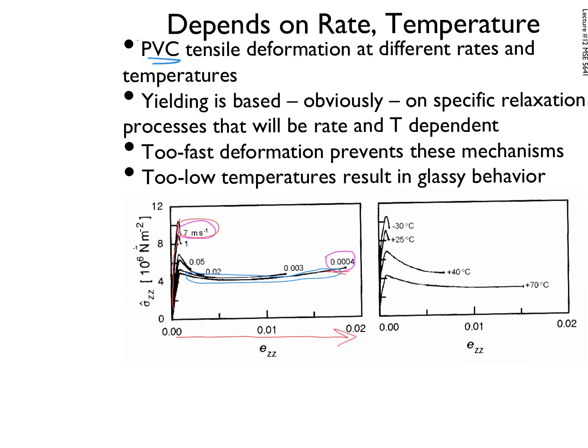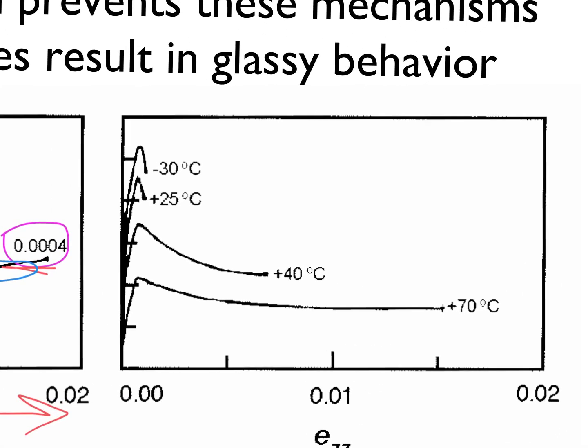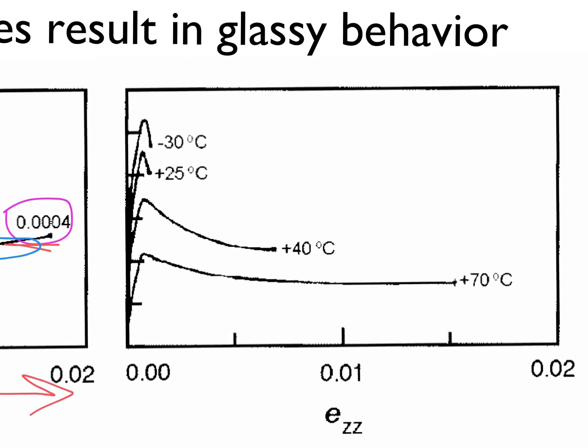And then in the context of temperature, we have a very similar behavior, and this is the one where the stuff at Home Depot becomes important. At 70 degrees, that PVC, and you never see this in the environment, about 45 degrees centigrade is like the Australian desert. At 70 degrees, you'd say PVC is relatively tough. At 40 degrees, it still looks pretty good. Room temperature, where we live mostly, except in this classroom, it tends to be relatively stiff, okay? And minus 30, it's also relatively stiff, okay? So what's going on there? First off, why is there such a huge difference?